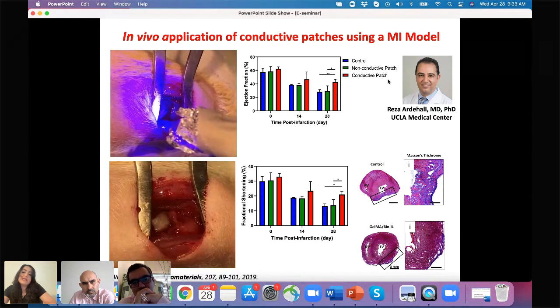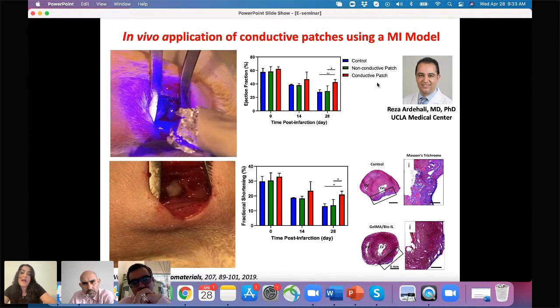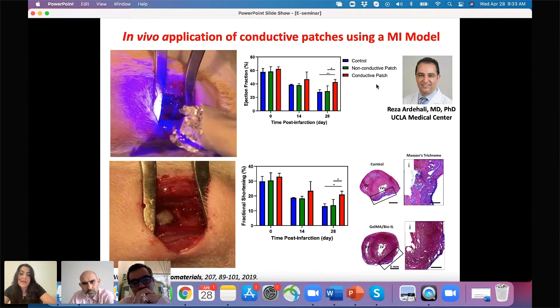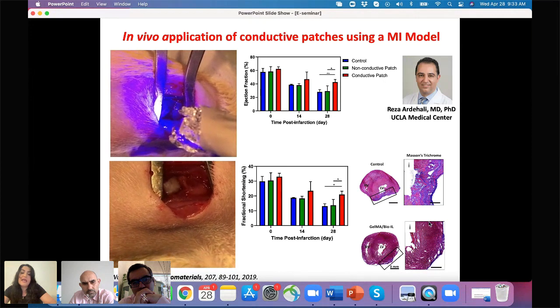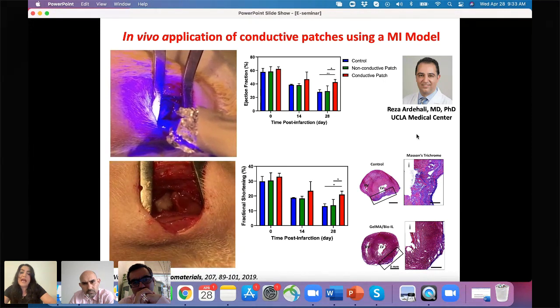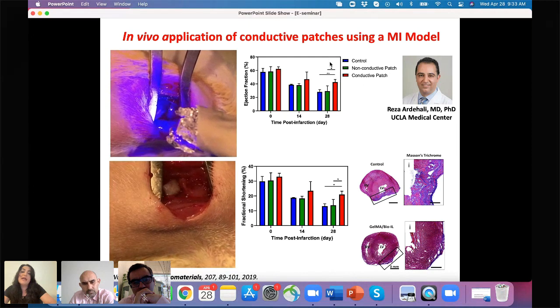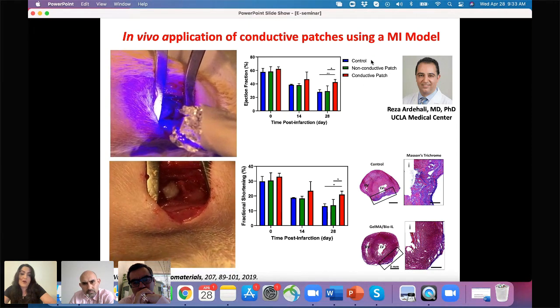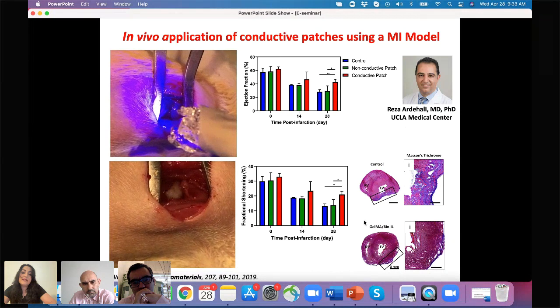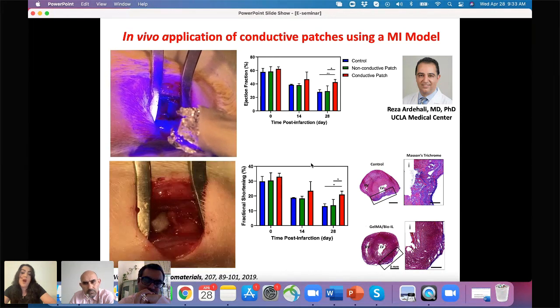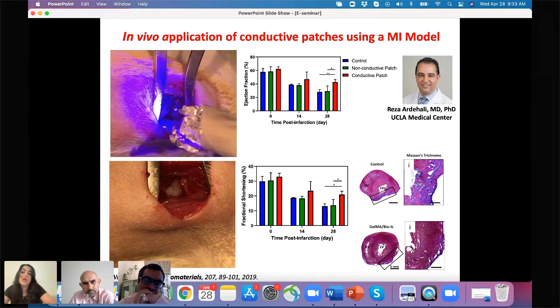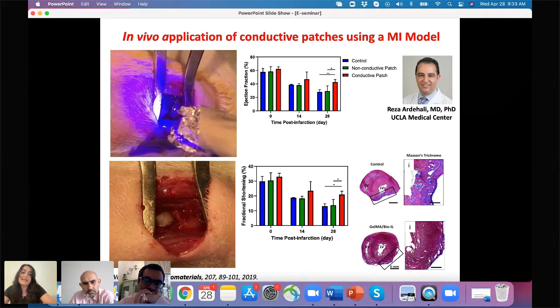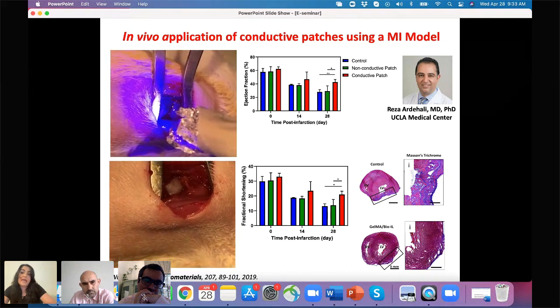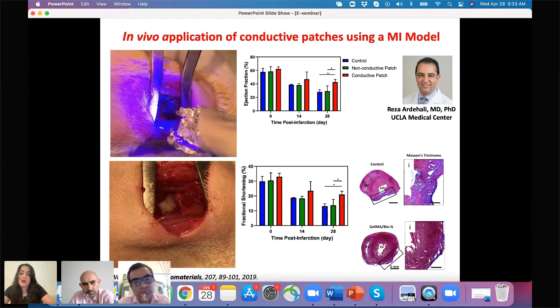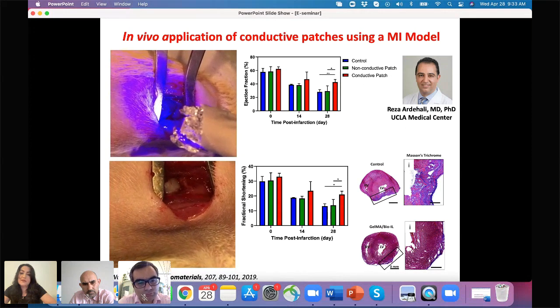time. Based on this experiment, we observed that the group treated with the conductive patch had better regeneration and increased heart function as compared to the non-conductive patch and also the control, which is the untreated heart. So this preliminary data, done in a mouse model, is encouraging. Our next step is to form larger patches and test them using an MI model in pigs. These are our ongoing experiments, and hopefully we get data soon.